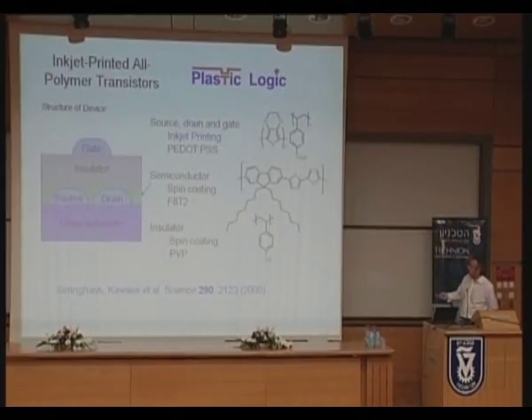So this is a paper we published in 2000 showing that we can make source, drain, and gate by inkjet printing a conducting polymer mixture. It has the acronym PEDOT:PSS. It's a material composition sold as an anti-static paint. We can paint or spin coat semiconductor and insulator, and we can use all three material types from polymer sources, and the transistors still work.